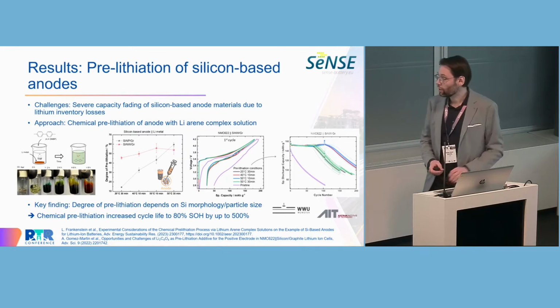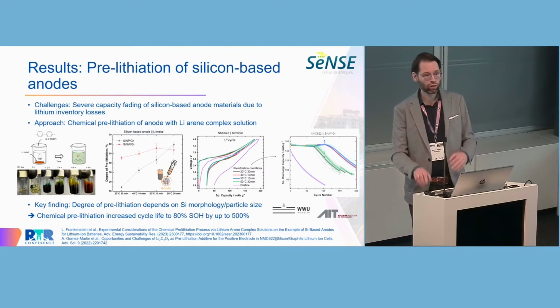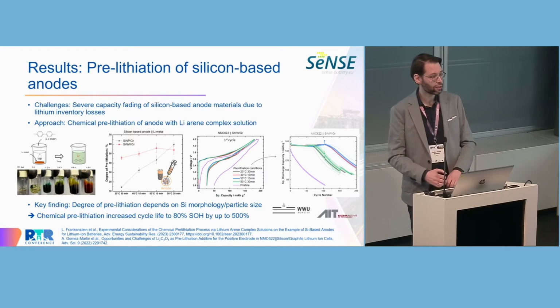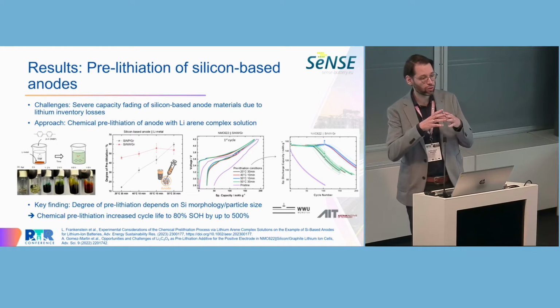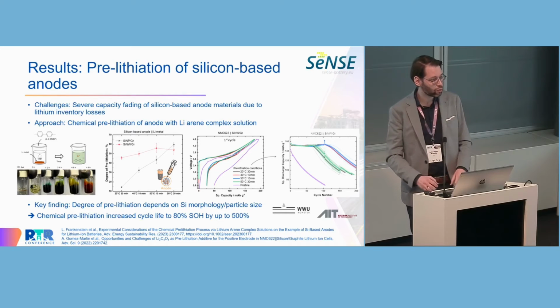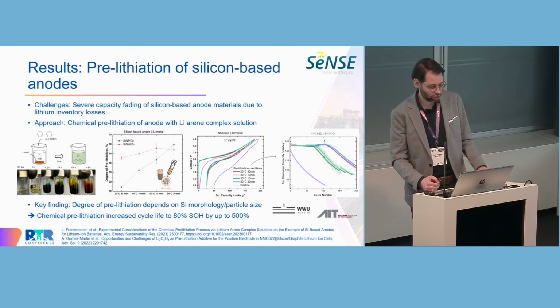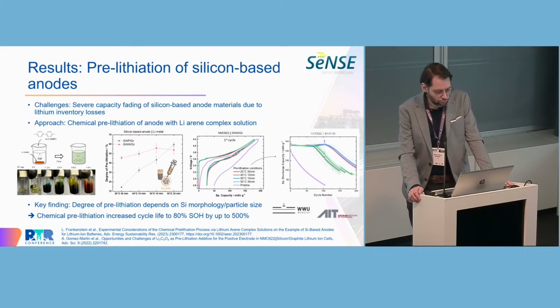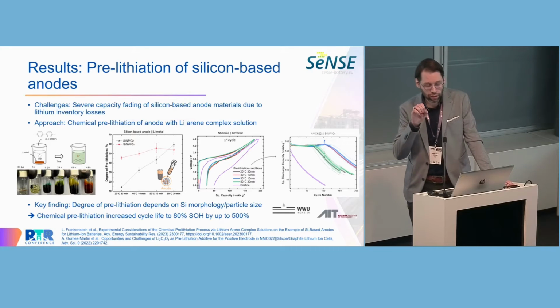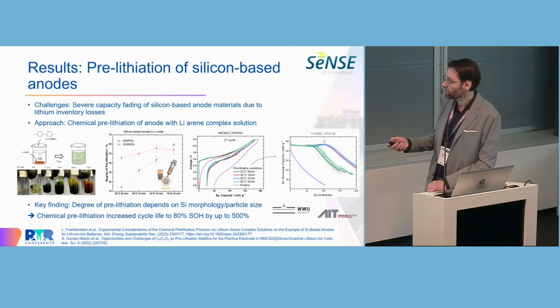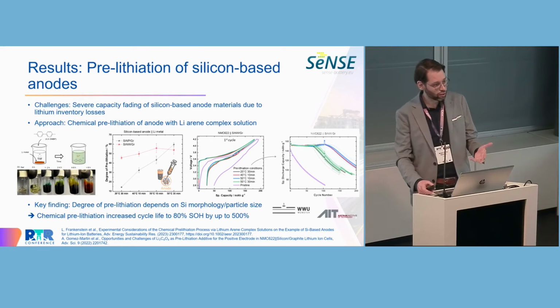Here an example on the anode side. As you probably know, silicon undergoes a really large volume change, and in each cycle you consume a lot of lithium because you always have to reform the protective layer that you need to suppress the electrolyte decomposition. One way to mitigate these lithium losses is to pre-lithiate the material. What that basically means is you introduce some lithium in the anode, in our case, before assembling the cell. We prepared a chemical bath containing lithium, and then we inserted the negative electrodes in this chemical bath